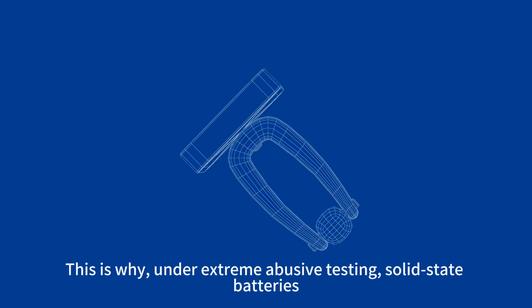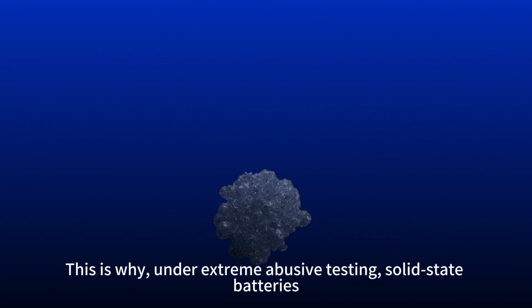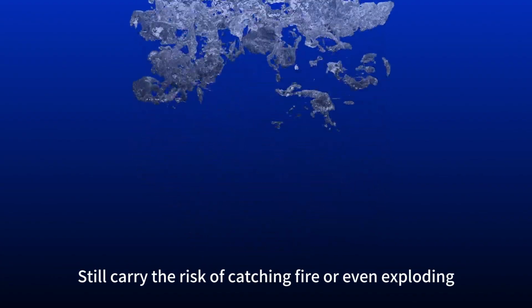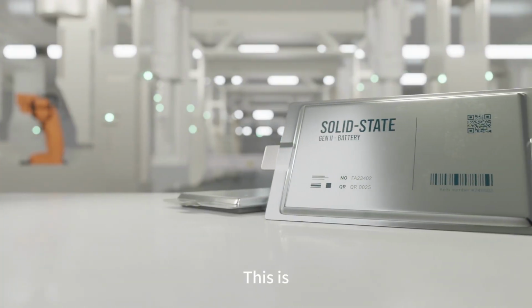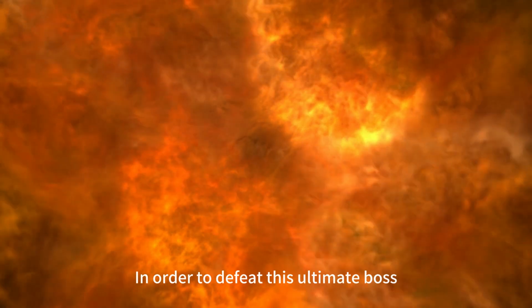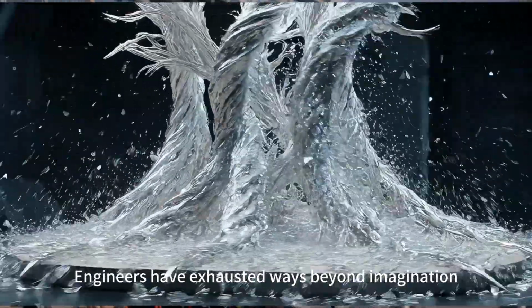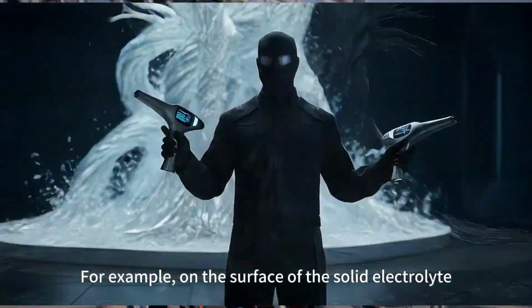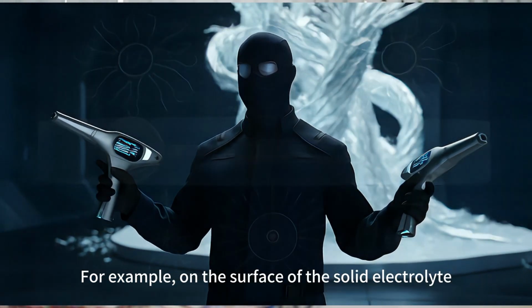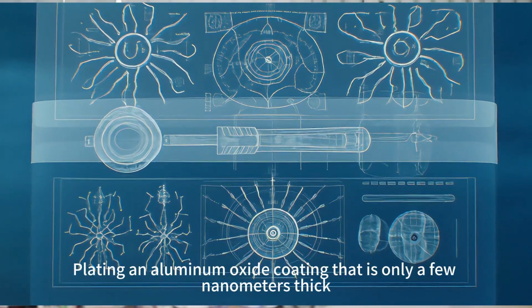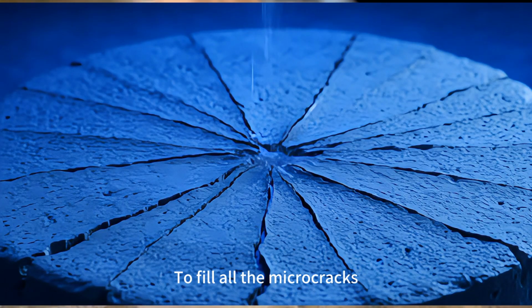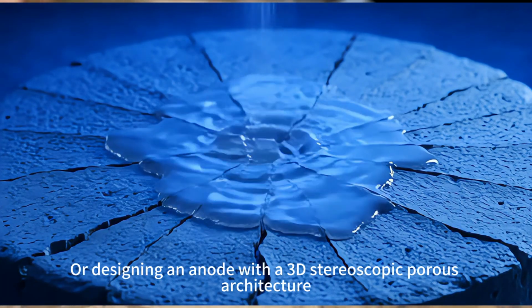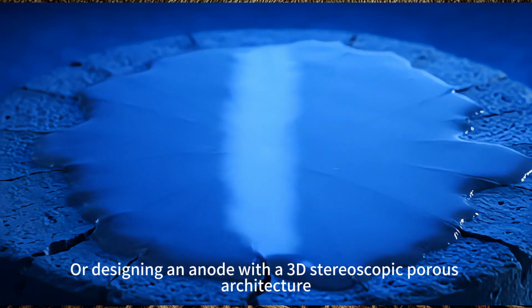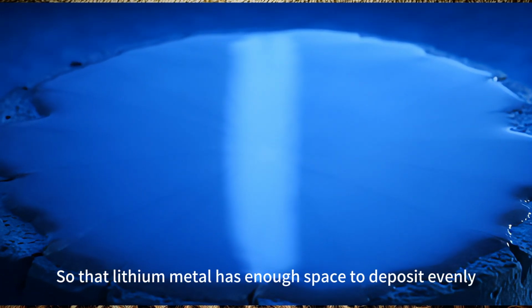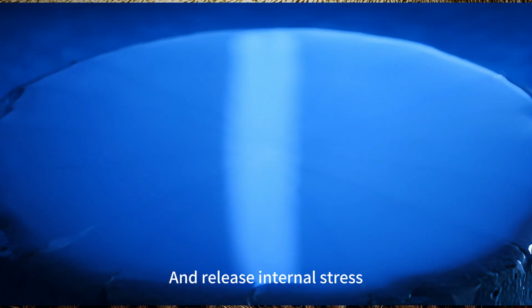This is why, under extreme abusive testing, solid-state batteries still carry the risk of catching fire or even exploding. This is the most extreme engineering challenge that engineers must face. In order to defeat this ultimate boss, engineers have exhausted ways beyond imagination. For example, on the surface of the solid electrolyte, plating an aluminum oxide coating that is only a few nanometers thick to fill all the microcracks, or designing an anode with a 3D stereoscopic porous architecture so that lithium metal has enough space to deposit evenly and release internal stress.